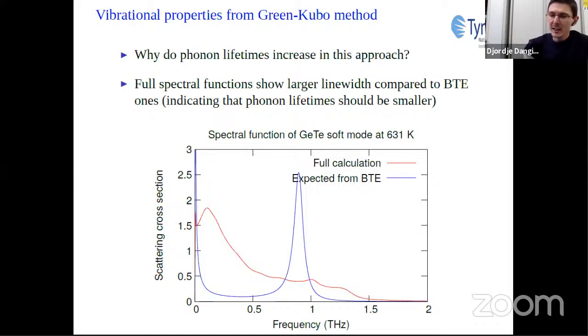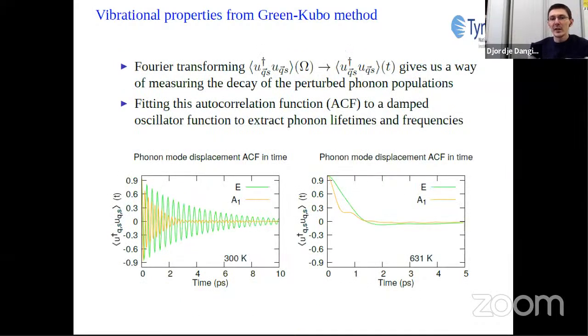To analyze this more deeply, we Fourier transform our spectral function into the time domain to get a time-dependent atomic displacement autocorrelation function. And we show this for two temperatures, 300 and 631 Kelvin. At 300 Kelvin, we get expected behavior for a relatively weakly anharmonic material, where we have oscillations and overall decay of the correlation. However, at 631 Kelvin, the anharmonicity is so strong that we do not observe any oscillation at all and only have the decay of the autocorrelation function.